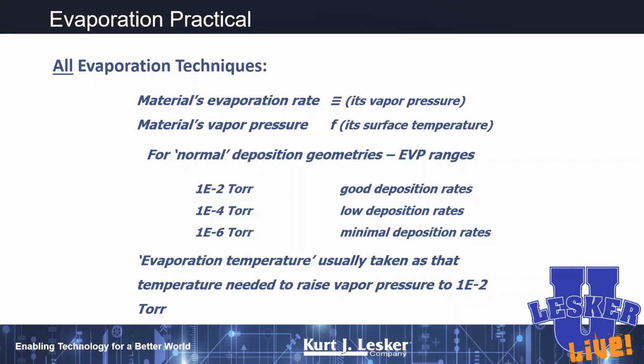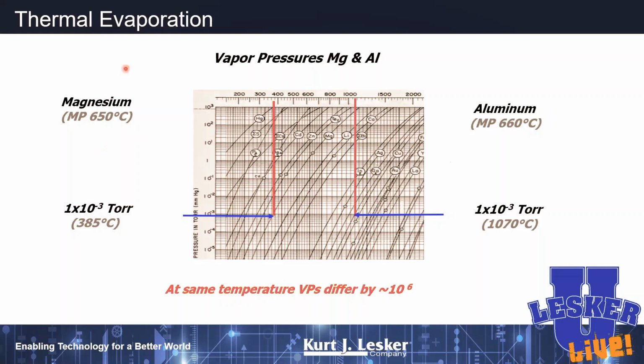Now, different materials need different temperatures. Here I'm showing you two different materials, magnesium and aluminum. Both have very similar melting temperatures, but notice that for magnesium, if I want a vapor pressure of 10 to the minus 3 torr, I only have to heat my magnesium up to 385 C. That's pretty neat. We won't be melting the magnesium. But for aluminum, because the intermolecular bonds in aluminum are so much stronger than in magnesium, to get that same equilibrium vapor pressure I have to heat the aluminum way above its melting temperature. It melts at about 660 C or so. So the aluminum is going to be molten. It's going to be very aggressive. It's going to try to drill holes through your boats or your crucibles. Aluminum is just really a nasty material to work with.